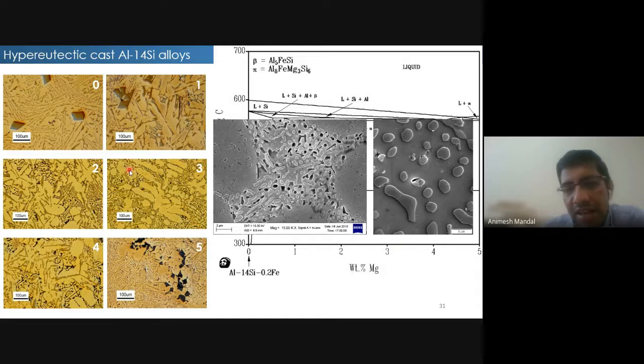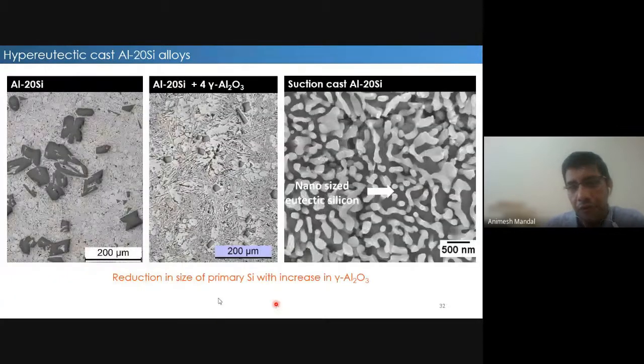And if you further heat treat this alloy, you can see the phases which you get. The Mg2Si phases which you get and the silicon are almost globular. It's almost spheroidized, that means it's almost round in shape, and this contributes to the improvement in the ductility of your alloy.